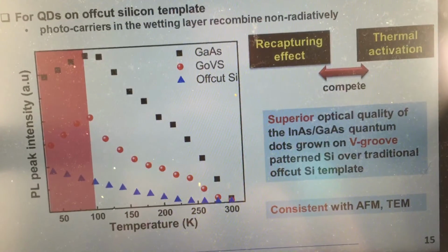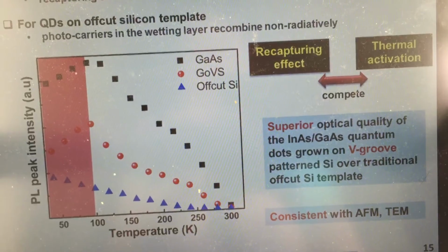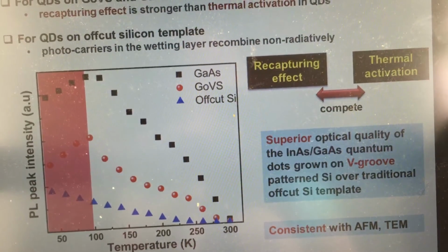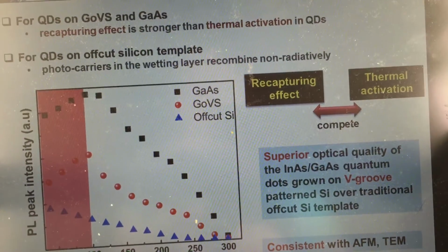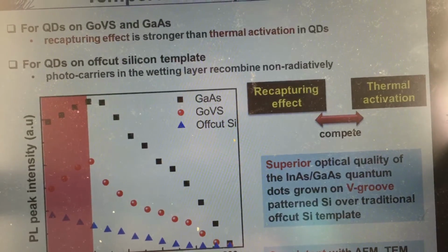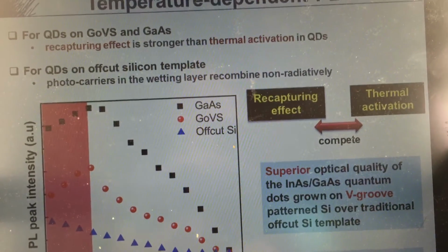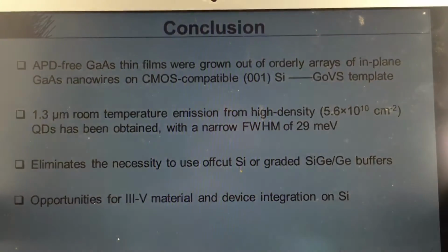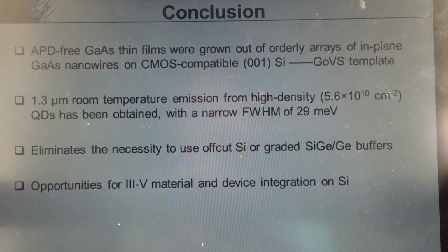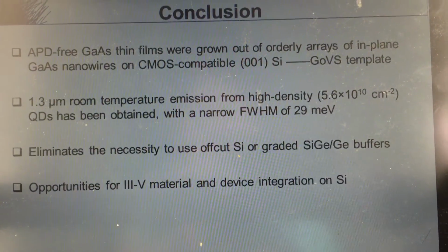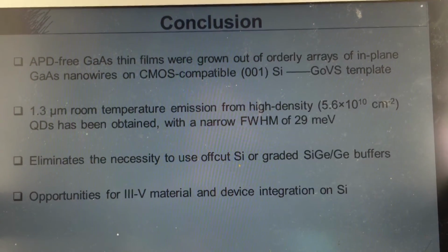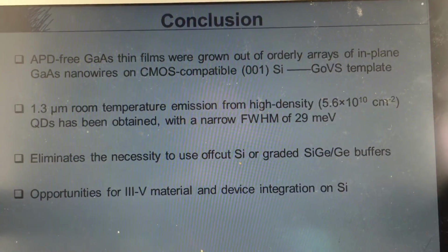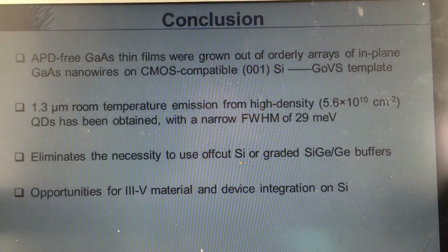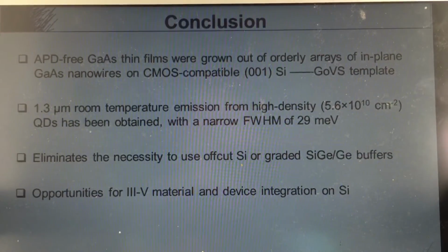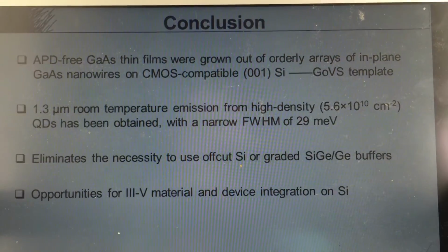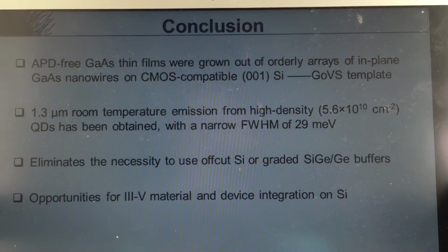This is consistent with our previous AFM and TEM analysis, where a higher density of coalescence and a higher density of defects penetrating the active region were observed on the off-cut silicon template. So here is the conclusion. We have got anti-phase domain-free GaAs thin films on CMOS-compatible 001 silicon substrate. And using this GoVS template, we have got 1.3 micron room temperature emission with a narrow full width at half maximum.